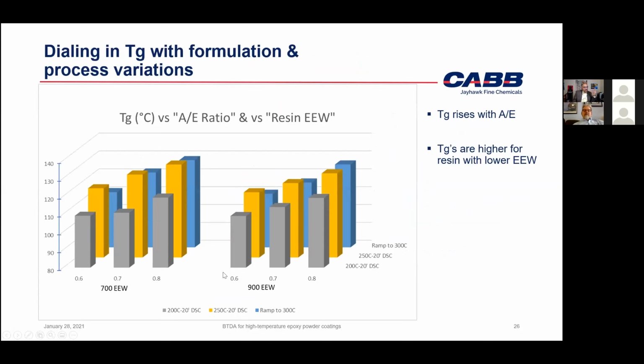Now, the 24-hour cure, we could not get the Tg out of every DSC run. So we couldn't compare all of those formulations in that way. And we didn't have the DMA results for all of the formulations. So we said, all right, forget the 24-hour cure stuff, but just look at the other curing techniques that Nicola ran in his DSC. So here you have the 20 minutes at 200C and 20 minutes at 250C, and then the ramp cure to 300C. So no matter which condition you look at, you can see a steady increase in Tg as the A/E ratio, the stoichiometric ratio, is increased. So more BTDA thrown in, the more Tg you get, more cross-linking you get, makes sense. And that happens for both the resins shown in this chart.